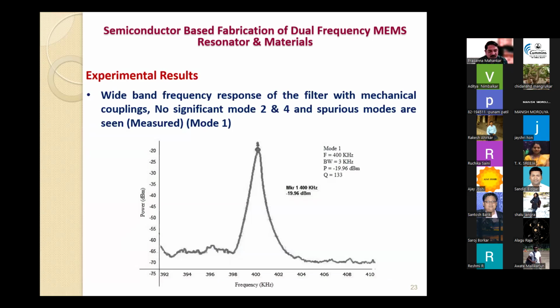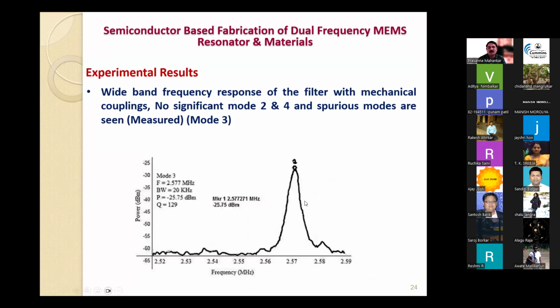This is the result when we applied the mode 1 frequency at 400 kilohertz. We got this response, which was almost minus 20 dB, and the Q measured was 133 in air and not in vacuum. As you can see here, the vibration modes 2 and 4, as well as any spurious modes, were also suppressed. You can see the signal waveform for mode 3 at 2.5 megahertz with a bandwidth of 20 kilohertz and a Q of 129 in air and not in vacuum. Again you can see at this particular frequency as well, mode 2 and mode 4 as well as spurious mode frequencies were